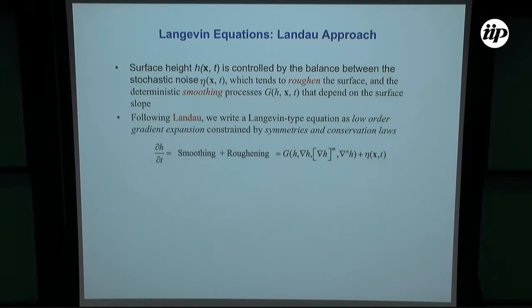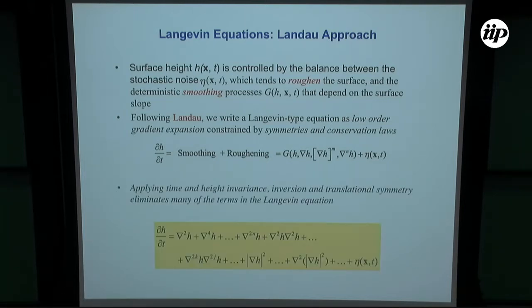What is the smoothing term? The smoothing depends on properties of the surface, how big the slope is. If the slope is large, you deposit atoms, they go down faster, they won't stick to the side. If it's smoother, the atoms stick. And so it depends on all these parameters. So which one of these are we going to keep? As Landau said, you have to write down all of the terms, and then choose all the ones that have roughly the same magnitude, because they will balance each other and give you the evolving surface.